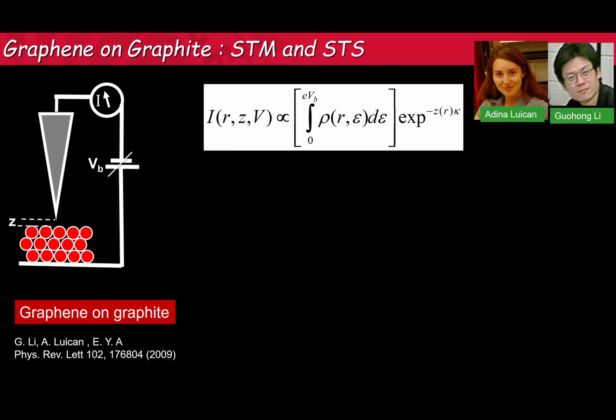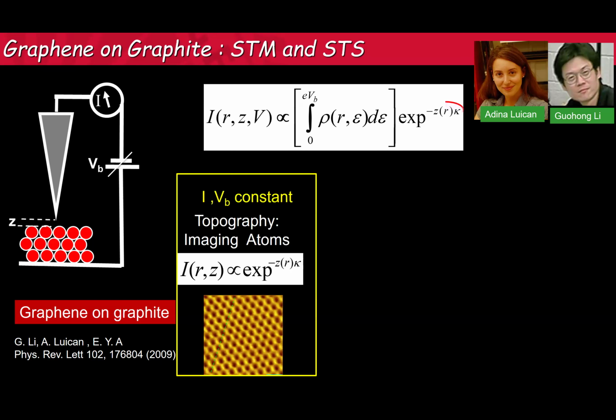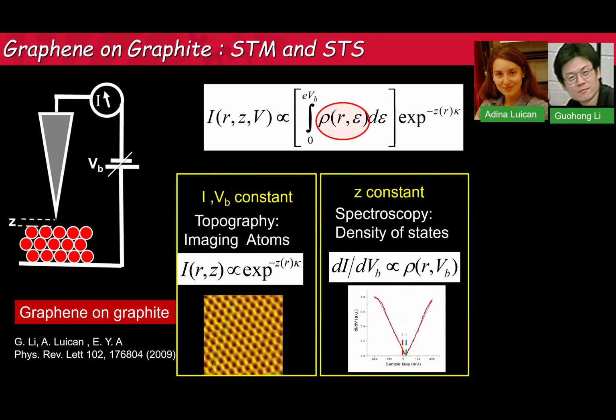And when you do that with STM, there are 2 things that you can measure. One is taking advantage of the exponential dependence on the height. Then you raster the sample and you see where the atoms sit, and you see the corners are the carbon atoms. And the other measurement that you can make is take the derivative with respect to the bias voltage, and that gives you something proportional to the density of states. And you see this is beautiful. We have recovered all the physics at the Dirac point here. The Fermi level in STM is always the origin, 0. So we see here we have a little bit of hole doping, and we can nicely separate Dirac point physics from Fermi level physics.